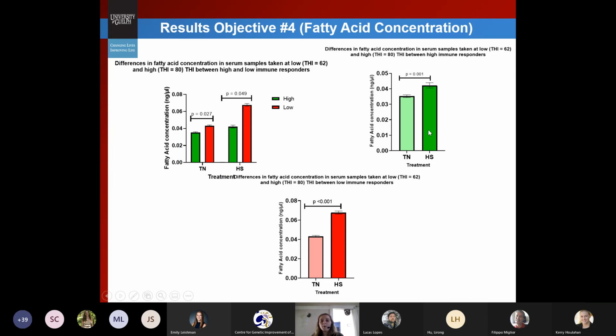So possibly indicating that they're using this cycle both at thermoneutral and heat stress more than what our highs would be. When we look within phenotype, though, across the treatments, we do see a significant increase in fatty acid concentration compared to at thermoneutral for our highs. So that could indicate that the highs are using fatty acid oxidation more at heat stress than what they would be at thermoneutral. But again, when we go back to comparing between phenotype, it seems that our lows tend to use it more readily than our highs would be. And additionally, we see an increase in fatty acid concentration at heat stress compared to thermoneutral for our lows as well.